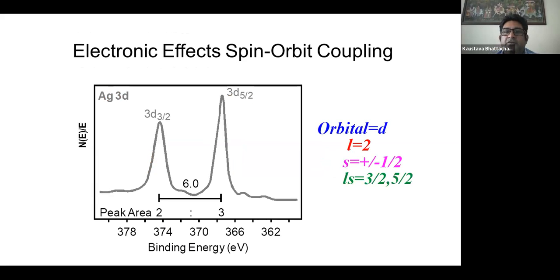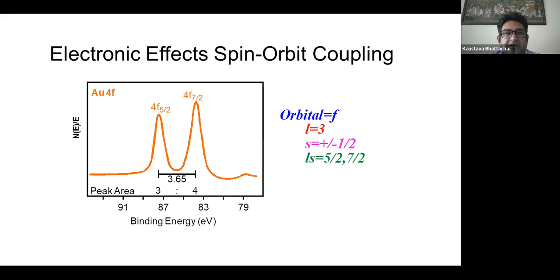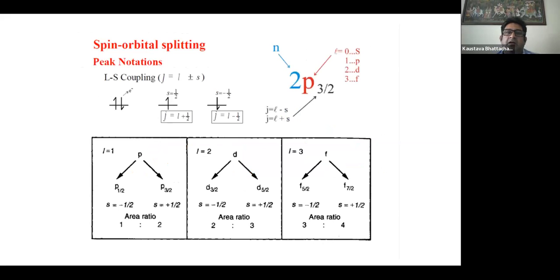Equivalently, for the d orbital, we will have 2 different peaks, 3d5/2 and 3d3/2, and obviously that will also have a particular splitting parameter. And for the f orbital, we will have f7/2 and f5/2. Similarly, we can also find out the population for a particular split orbital. We know that the population is given by 2j plus 1. For a p orbital, the ratio is 2 times 3/2 plus 1, that is 4, to 2 times 1/2 plus 1, that is 2, so 2:1. So the area ratio of p3/2 to p1/2 should always be 2:1. If the area ratio is not 2:1, then there is something more to it that we should try to understand.